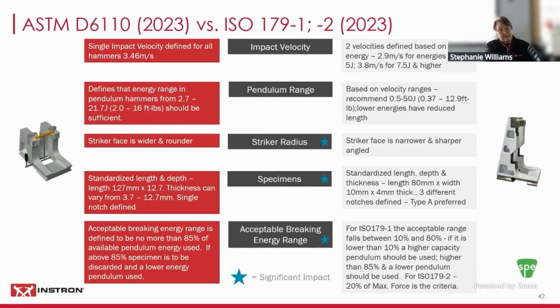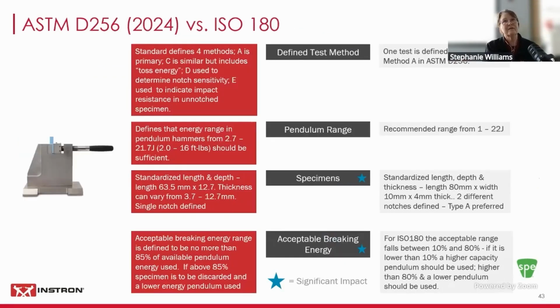They say that the energy absorbed has to be higher than 10% of what's available, but less than 80%. And if you're running fully instrumented, you have to be below 20%. You can't cross 20% of what the maximum capacity is of the load cell. ASTM D256, we look at the same.